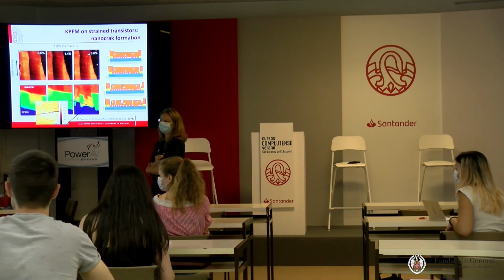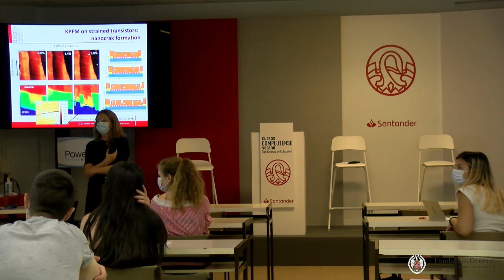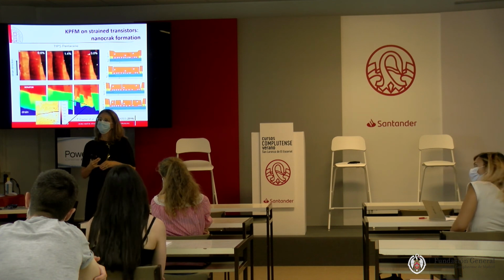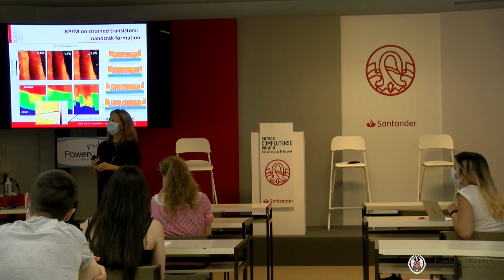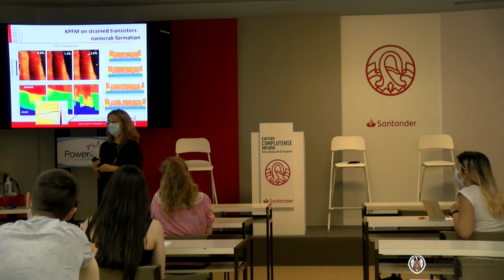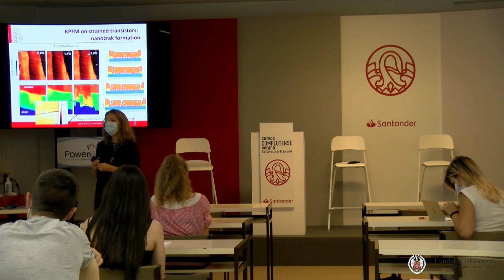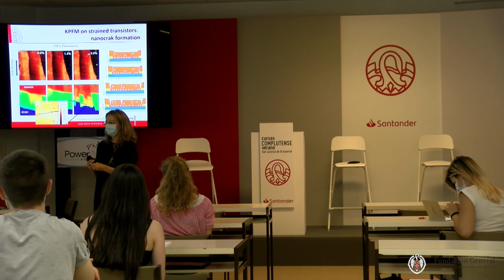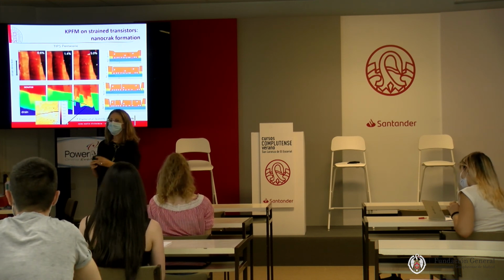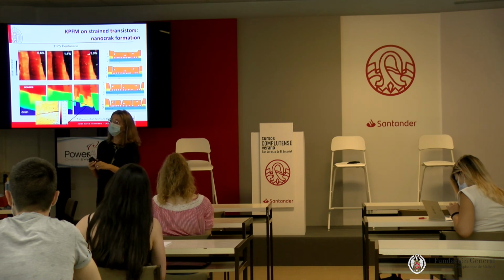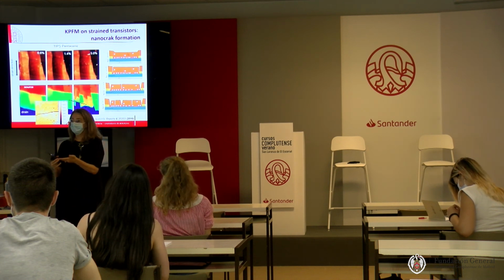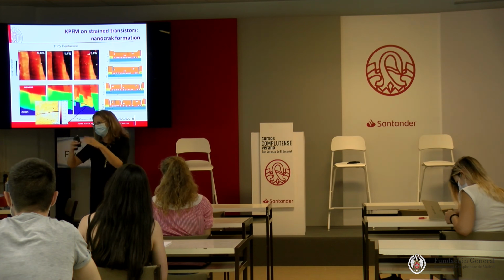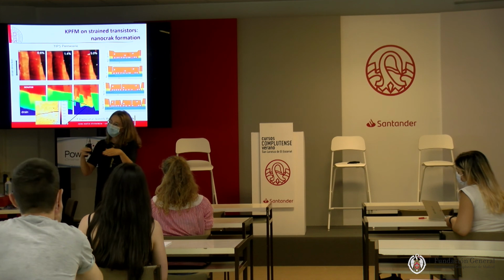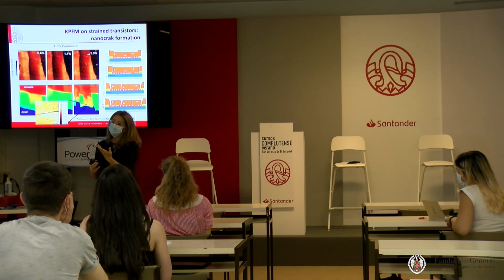I wonder, is the TIPS pentacene stable under oxygen? Yeah, under air, I mean regular air. Can you operate it, or do you need to cover it? No. We operate them in room air and light. They're okay, honestly. They're not too bad. They're more stable. I don't know if you know Marta Mastorren at ICMAB in Barcelona. We did with her a blend of polystyrene and TIPS pentacene with the bar-assisted coating. And the polymer blended with the TIPS pentacene was found to stabilize it because it kind of seals the top. So the idea is that if you do a proper blend, you can even stabilize it further. But it's relatively stable.